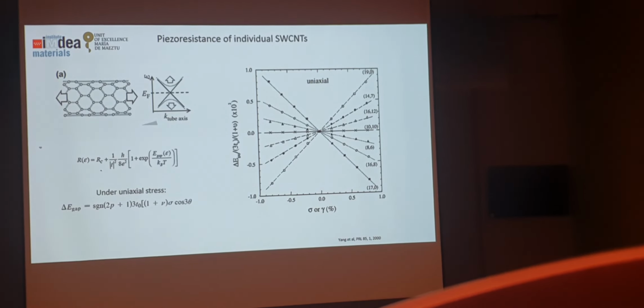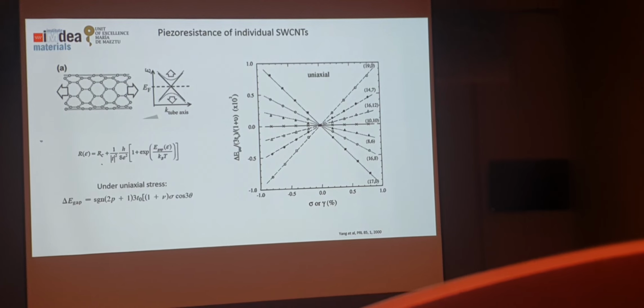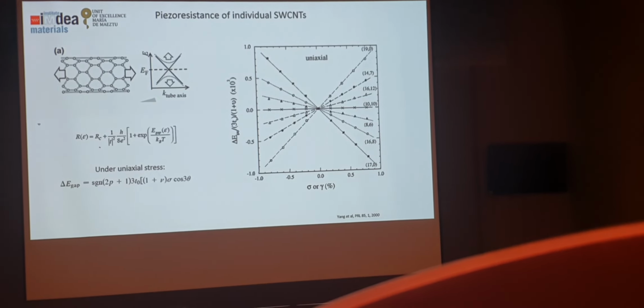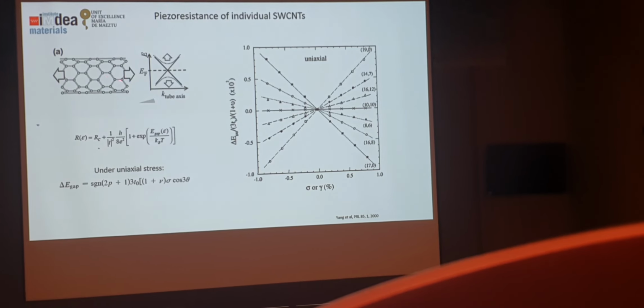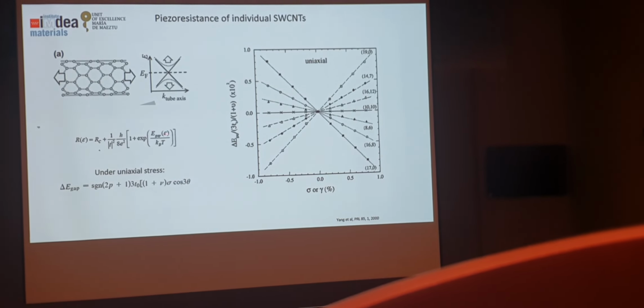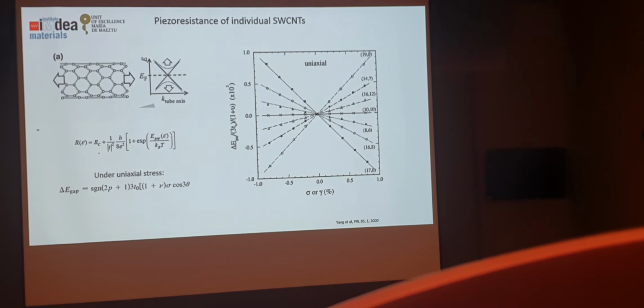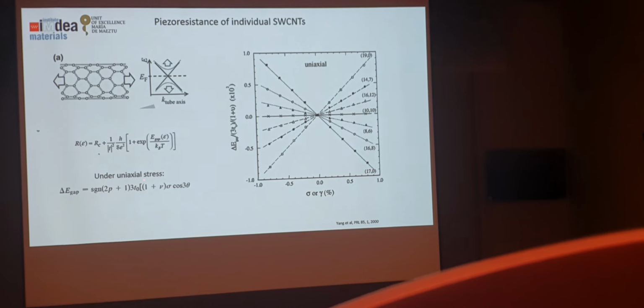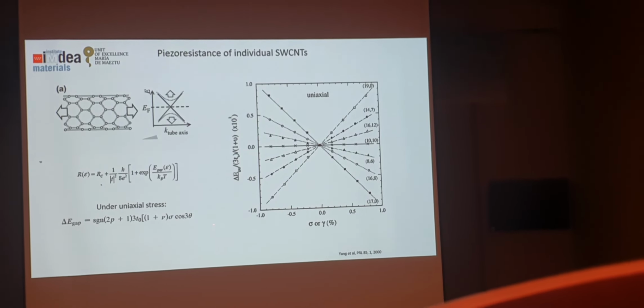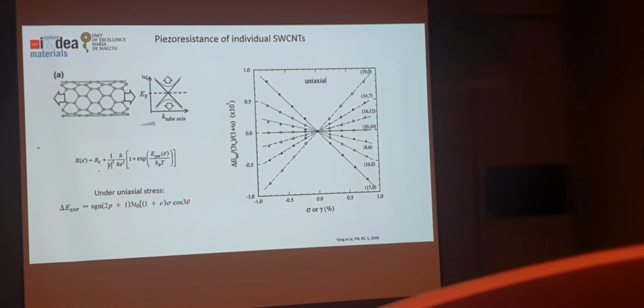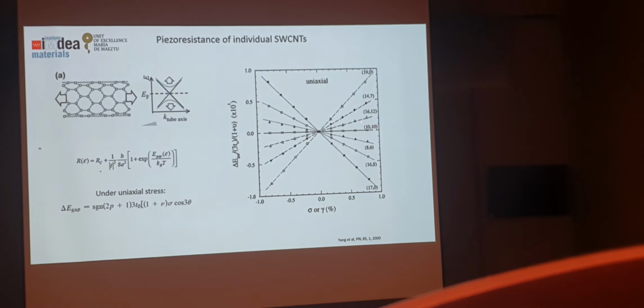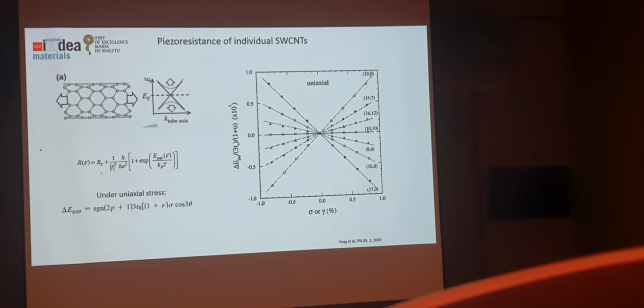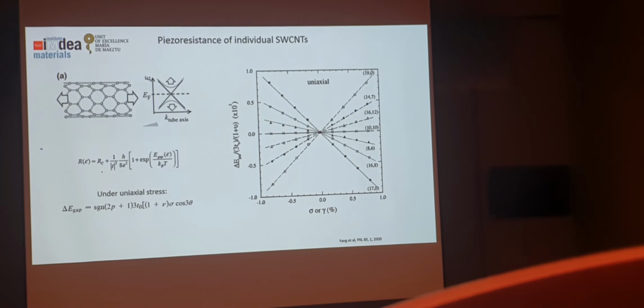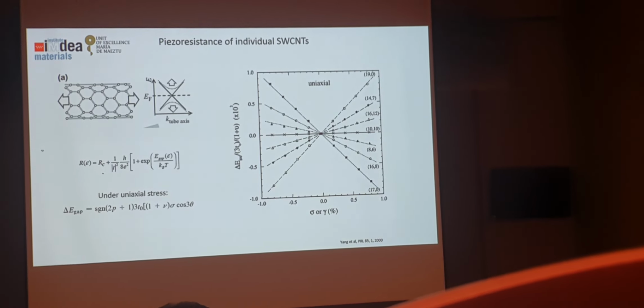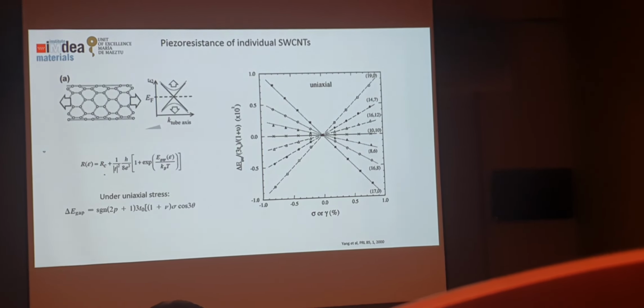Now, if you look at the literature and what I think is the best understanding of piezoresistance in individual CNTs, right? So people have looked at that in detail, and essentially the idea is if you take a nanotube, the resistance will depend pretty much exclusively on the band gap, and that band gap will open as you stretch it, right? That's relatively well known. The trouble is that a band gap will open only if they are not armchair, so only for certain chiral angles. So this is the prediction of piezoresistance, and you can see, for instance, this (10,10) tube, no piezoresistance at all. So this predicts that only certain chiral angle single nanotubes would be piezoresistive. And that is for individual tubes.